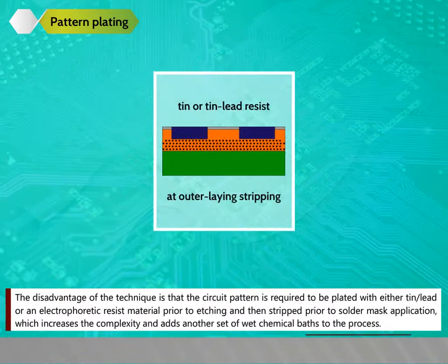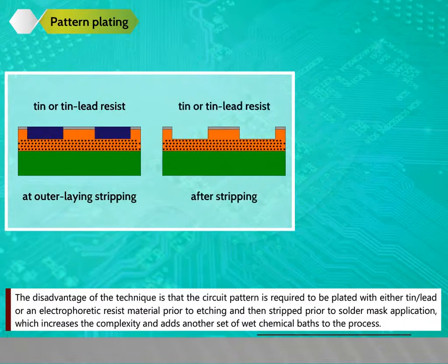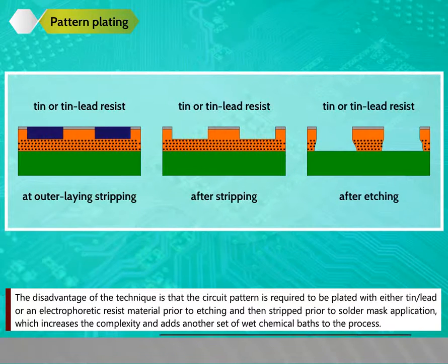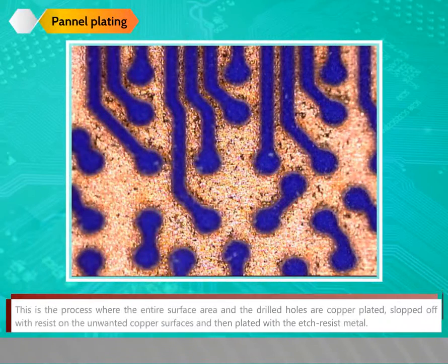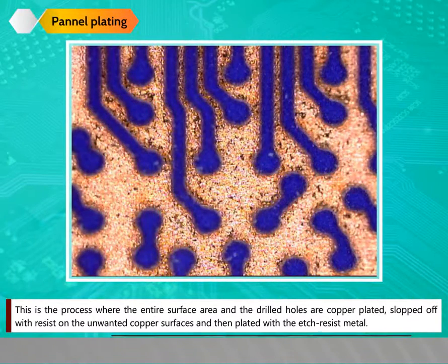The disadvantage of the technique is that the circuit pattern is required to be plated with either tin or lead or an electrophoretic resist material prior to etching and then stripped prior to solder mask application, which increases the complexity and adds another set of wet chemical baths to the process. Panel plating. This is the process where the entire surface area and the drilled holes are copper plated, stopped off with resist on the unwanted copper surfaces and then plated with the etch resist metal.